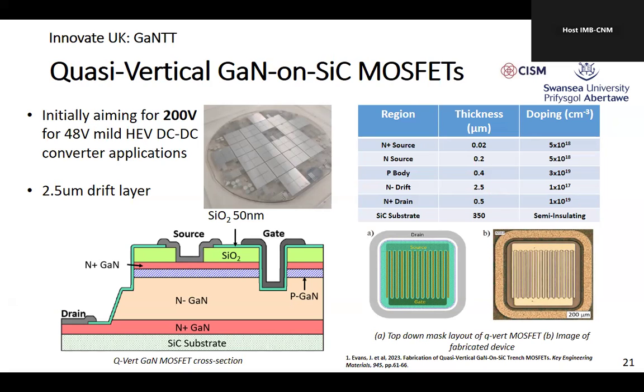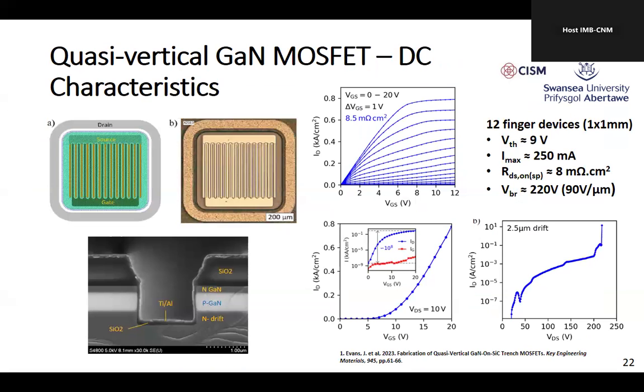But by all accounts, it's a vertical device, and you've got some of the parameters around here about the doping concentrations that we use. And this is what it looked like in plan view. You see the drain around the edge there, and the source and gate in the middle part of the die. We use a 2.5 micron drift layer to block the voltage for this type of device. And there are some initial characteristics. We got some very nice classical output characteristics for the device for different gate voltages.